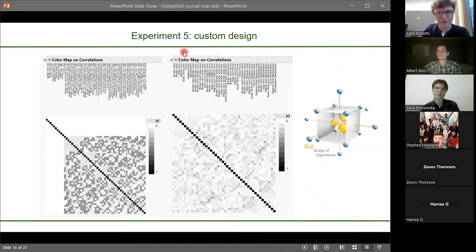So the next thing we did is a custom design. Basically this is a correlation color map of the first experiment, the definitive screening design. What it's showing is this white area. The definitive screening design screens for primary interactions, your main effects, and any basic interactions between variables. This whole grey area, the more complex interaction zone, it just ignores, so you get a lot of confounding, where you can't unpick the complex interactions going on between lots of different variables. And that was 24 experiments, or 25.